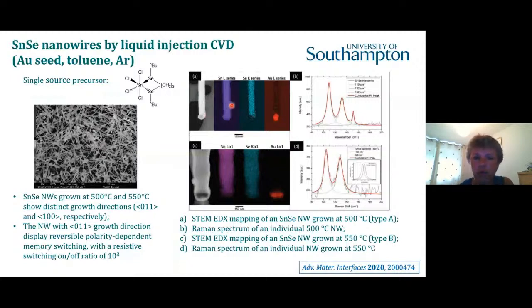What you can see is we've got quite nicely defined tin selenide nanowires. You can see the gold seed at the end of these nanowires, and we can follow this by Raman spectroscopy and look at the X-ray structure and so on. If you take the temperature up a little bit, you change the direction of the growth. You go from a 011 growth direction, which is the figure at the top, to a 100 growth direction, which is the figure at the bottom, just by changing the growth temperature, which is, again, I think the point really to emphasize is we're getting a remarkable level of control, way beyond the level that we would have anticipated when we started out in this project, that we can control orientation, growth direction, the one-dimensional structures, obviously, and the two-dimensional structures that we've seen already.